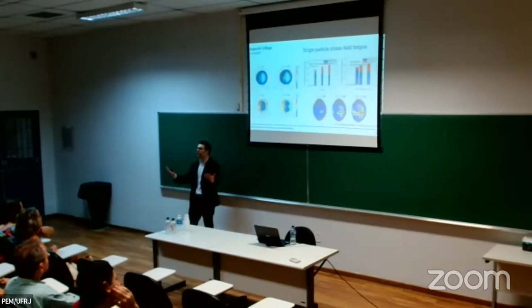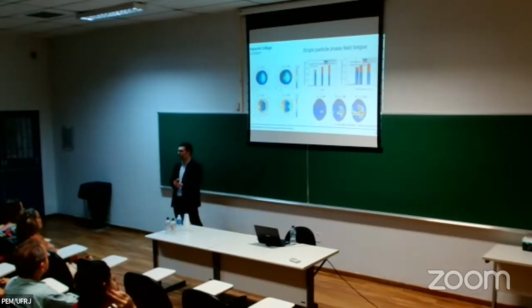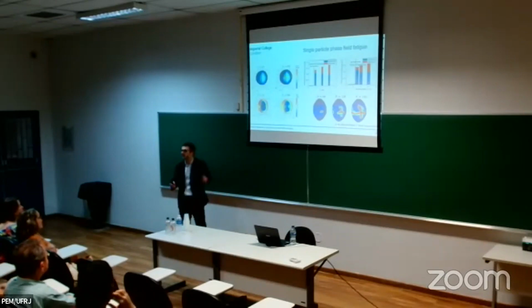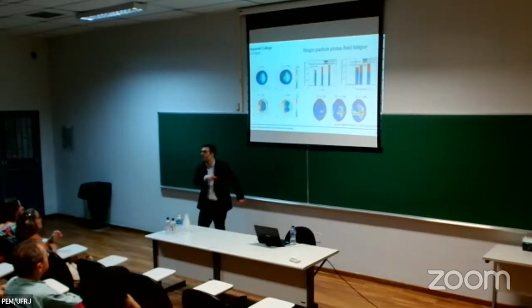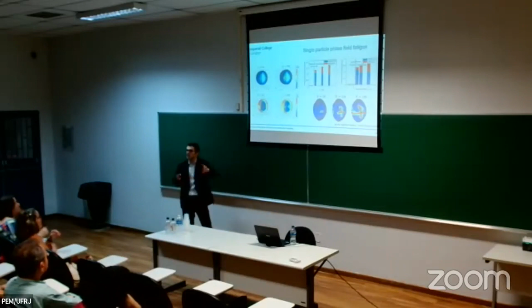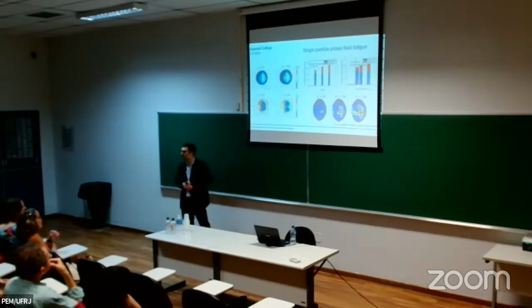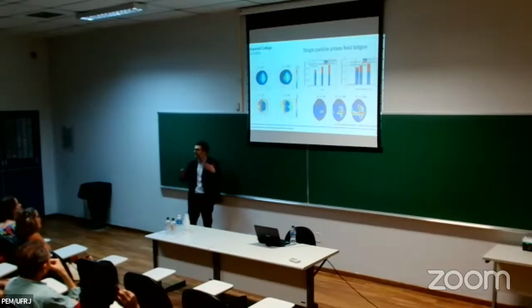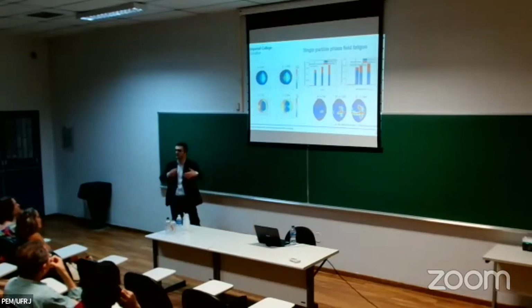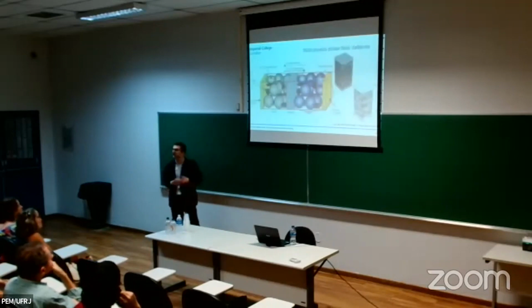And then we can use this virtual platform to map safe regimes of operation. We can, for example, change the charging rate, the C rate, and determine the threshold below which we will not see cracks appearing in those particles. And we can also change, for example, the particle radius and determine the largest particle that will not give you cracking problems for those loading conditions. So this is quite useful in terms of mapping safe regimes of operation and determining the right use of those batteries.